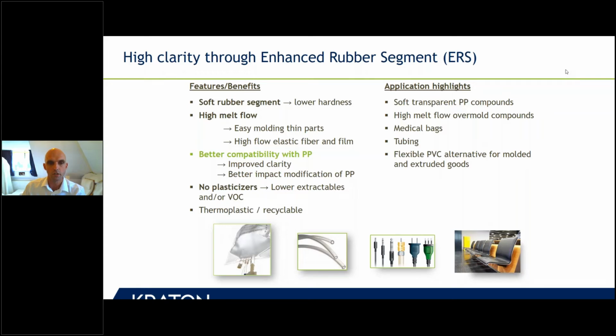So you have more branching, basically. It's like a short chain branching. And that gives a very soft material. So it also increases the melt flow of the polymer. So it helps processing. And it's getting softer, so you can do without plasticizers, which is of course good news if you want to look at medical applications where you don't want extractables. Moreover, the compatibility with polypropylene is better, and through this higher compatibility, you get clearer compounds.